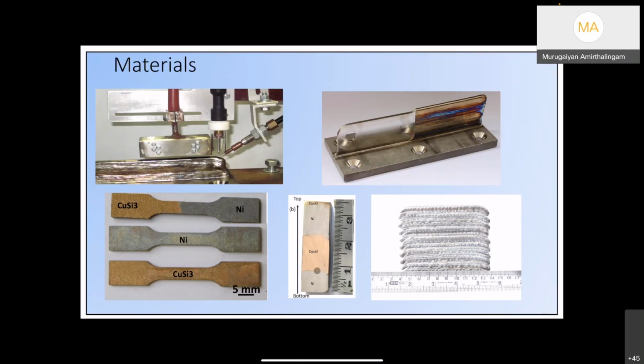So here it is not like just changing the wire at this point. We can also gradually change, so that you start with the nickel wire, and then you reach the interface, you slowly change the composition so that it becomes, say, nickel 10% copper, nickel 20% copper, ultimately 100% copper. Similarly, you can also smoothly vary the composition by changing the melting rate, for example, so that we can get a nice functionally graded material as well. And these are some advantages we gain.